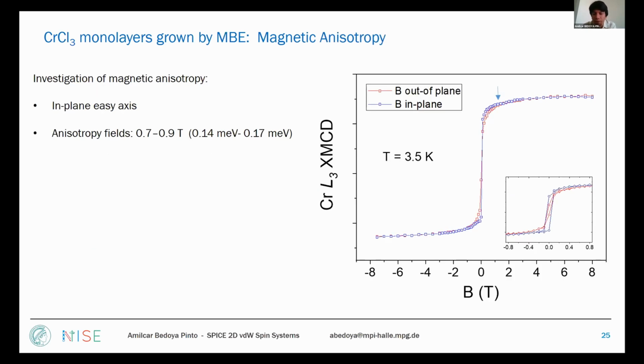Then, of course, very important is the anisotropy. The anisotropy we try to measure with grazing and normal incidence to see how it behaves when we have the sample in or out of plane. And you see that the easy axis is clearly in plane, as you see from here on the right-hand side. And the anisotropy fields are relatively large compared to what we were expecting. That was between 0.7 and 0.9 Tesla.